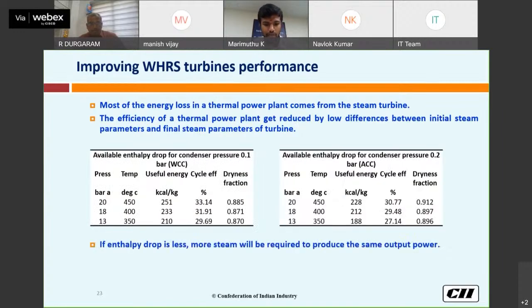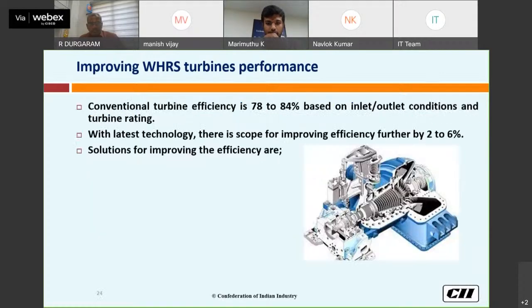Now you can see in the table on the left side. If the mainstream temperature is high, my cycle efficiency will be 33. If it is less, for example 13 bar and 350 degrees, the efficiency goes down. So if the enthalpy drop is less, more steam will be required to produce the same power. That's why we are getting low efficiency in the WHRS turbine.